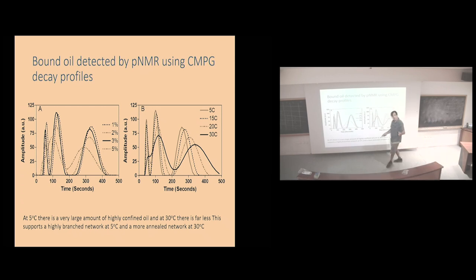Now, do you remember the pulsed NMR for solid fat content determination? That machine is a really practical way of determining spin-spin relaxation times, or spin-lattice relaxation times, T2s. I was talking to some of you about the fact that you can use it to determine the T2 of water, which changes like crazy in hydrogels, from 2,800 milliseconds to like 100, depending on what surface you present to it. So it's a paper-generating machine, because the changes are so gigantic and sensitive to surfaces. I highly recommend this fantastic 20 megahertz NMR, the same one used to do SFC. If you pay the extra money, you can do T2s and T1s. And you don't have to bother the guy with the 800 megahertz NMR.